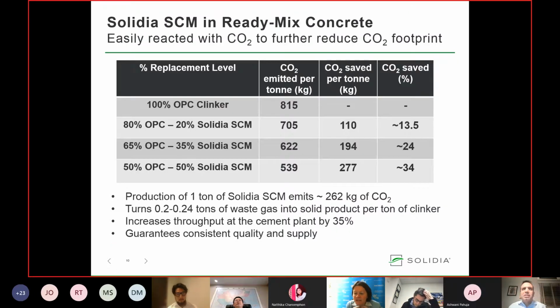And in this slide, can you please try to conclude? How much CO2 can we save if we were to use Solidia SCM in OPC? At different replacement levels, for example, if I have a blend of 20% Solidia SCM, then we are talking about 13-14% CO2 reductions. If we go to 35% replacement, which is our typical blending capacity, we are talking about 24% CO2 reductions. And in some applications, we can go as high as 50% replacement. In this case, we are talking about 30-35% CO2 reduction.